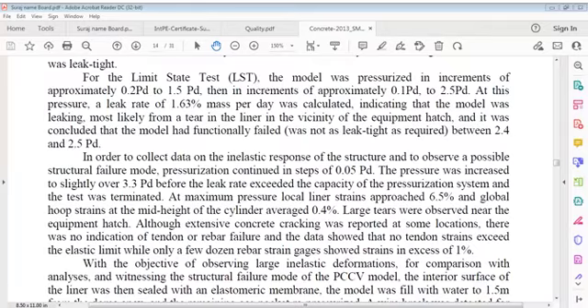For the limit state test, the model was pressurized in increments of approximately 0.2 PD to 1.5 PD, then in increments of approximately 0.1 PD to 2.5 PD. At this pressure, a leak rate of 1.63% mass per day was calculated, indicating that the model was leaking, most likely from a tear in the liner in the vicinity of the equipment hatch. It was concluded that the model had functionally failed, not being as leak tight as required, between 2.4 and 2.5 PD.